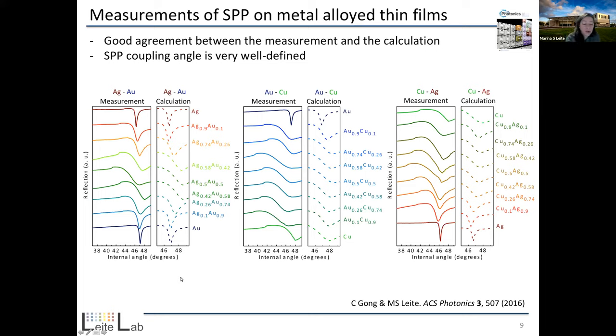Now, in order to corroborate these ellipsometry measurements, because as you can imagine, we heavily rely on the model, as I mentioned a few times, we then can do a very complementary type of measurement, which is a measurement of a surface plasmon polariton using something that we call the Kretschmann configuration. And basically what we do now, we actually scan as a function of angle, these metal dielectric interfaces, and look for an angle in which we have a minimum in reflection.